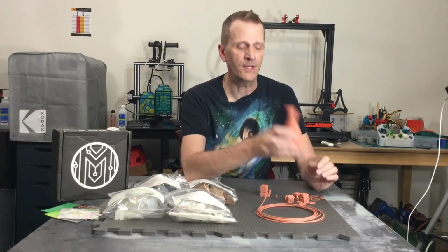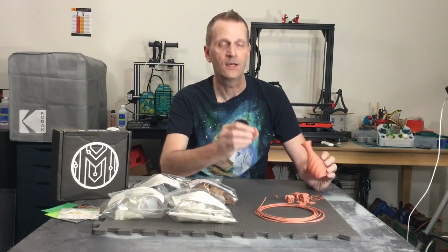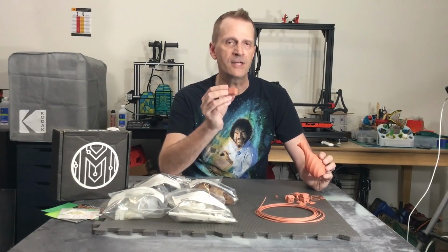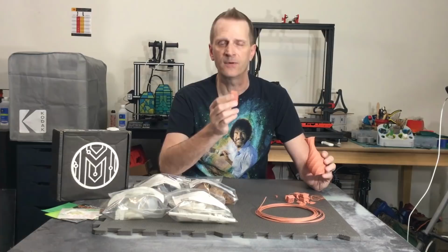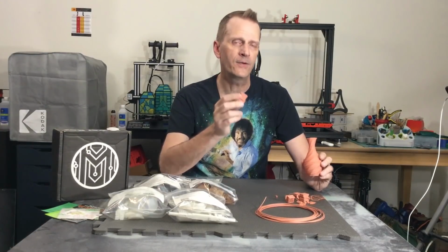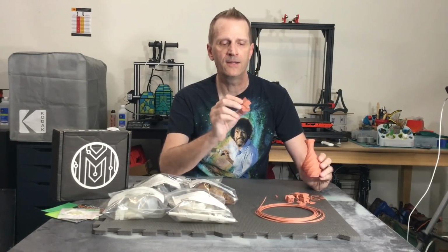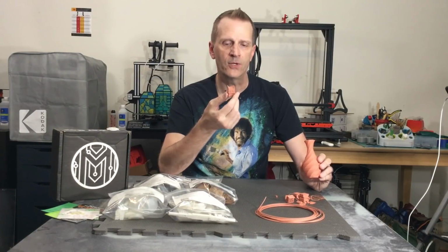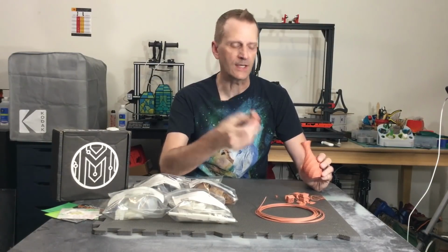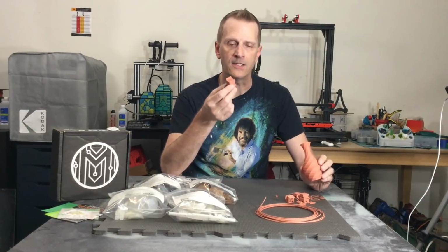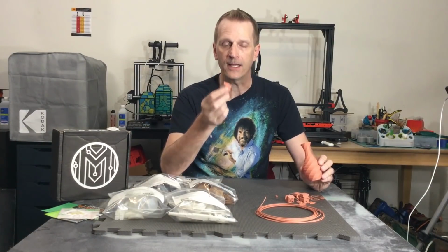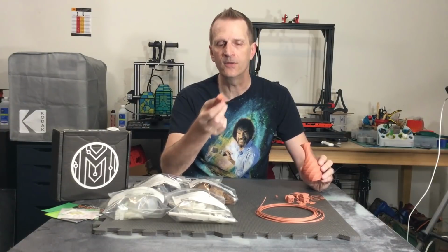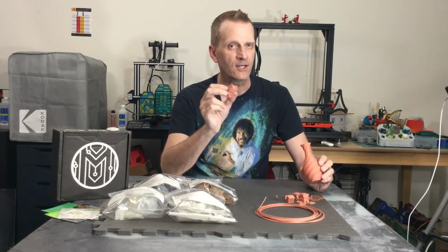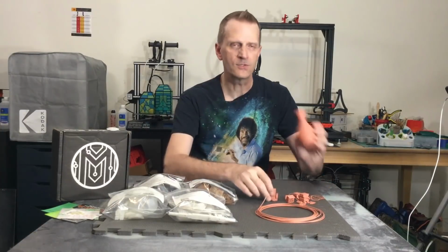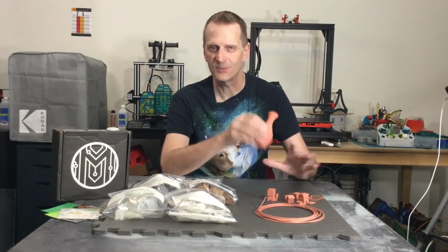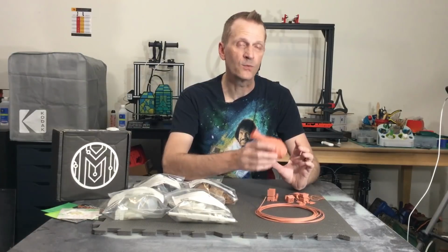I believe what's happening here, and I may be wrong on the scientific analysis of this printing, is we're actually kiln firing this type of filament as we print it. With the powder that's added and the temperature of the bed and the hot end, it's kind of almost like you're putting this through the kiln as you're printing it. Now maybe we could take this and add a glaze to it and put it into an actual kiln, but I think the amount of plastic that's in here already, this would just disintegrate. So going past all that speculation of what happens during the printing, it's a really unique filament.